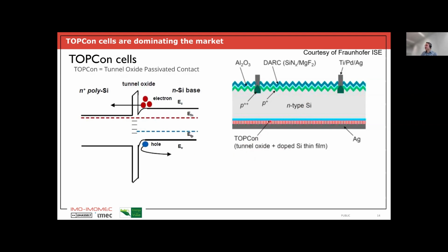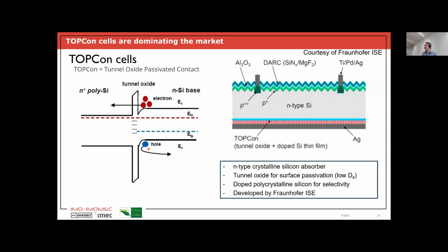So now at the rear, we will, for instance, attract the electrons to come to that place, but we will reject the holes. So we get a very good surface passivation at the rear. And this actually leads then to the potential of reaching very high conversion efficiencies. And so late last year, the record for this type of device in terms of cell efficiency was set by a Chinese company, Trina, and it's around 27.1%. So it's really very high efficiency and much higher than what you can reach with PERC cells.